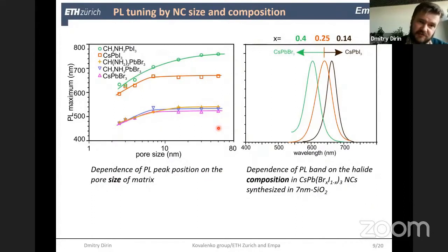So here is the summary of the previous slide, just to show that we can tune the PL maximum by both composition and size. And also that we are not limited to pure compositions like cesium lead bromide and cesium lead iodide. We can also make a mixed cesium lead bromide iodide. It's similar to colloidal lead halide perovskite nanoparticles, which we have shown before, but here we show that it also works in mesoporous silica synthesis.